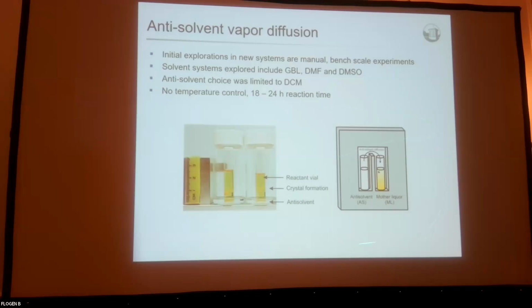If we're doing it on the robot deck, this is like an excised version of what our block looks like, where we have individual vials for the anti-solvent and for the mother liquor. Crystallization tends to occur at the top where the concentration of the anti-solvent is greatest, inducing crystallization. Of the solvent systems that we look at, a lot of GBL seems to work the best. DMF and DMSO are less appropriate solvents in that the products are too soluble and it's harder to achieve the critical concentrations required for nucleation and crystallization. No temperature control is required in this system, which is nice with respect to a lot of the ITC work.